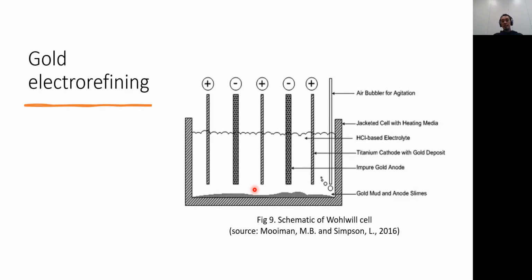Once the gold bullion reaches 99.5%, it will go through this Wohlwill cell, or an electrorefining cell. The electrorefining cell is mainly comprised of three main elements: a cathode, an anode, and electrolyte. So in this gold electrorefining, the gold will dissolve from the anode. The anode is the impure gold, 99.5%, and then the gold will dissolve and be deposited